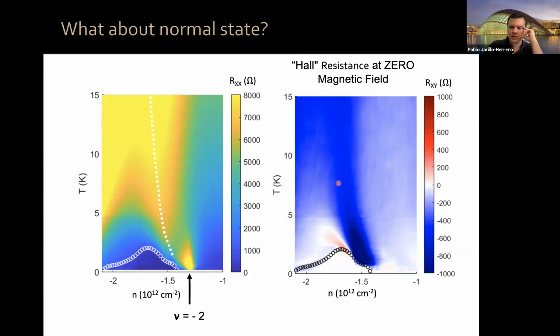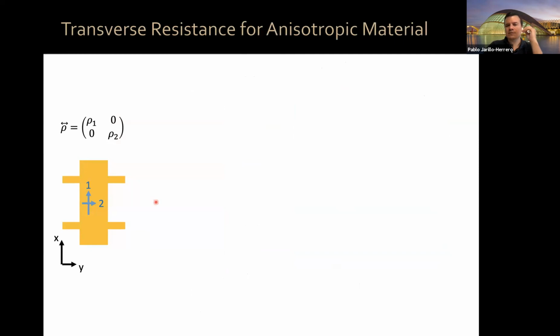Okay, so let's look at this a bit more carefully. But first, let's think about why you would have, and by the way, the region where this RXY is very strong is the same region as where you have this resistive ridge, the banana, okay? So why would you have a transverse resistance at all, okay? Well, this is something which can happen for anisotropic materials, okay? So your resistivity tensor, in 2 dimensions, you have ρ1, 0, 0, ρ2, okay? This is if your device axes are aligned with your crystallographic axes, okay, then you expect to measure 0 transverse resistivity, if you measure transverse voltage here.